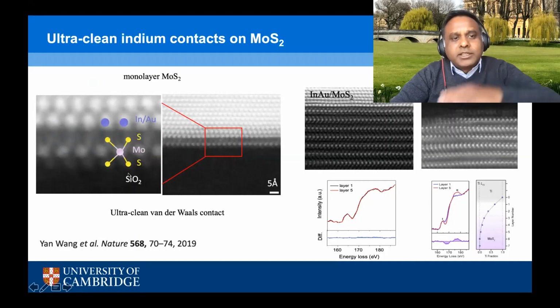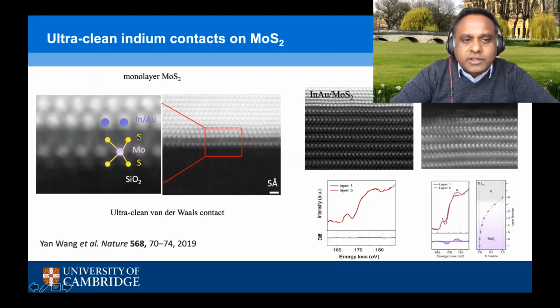And so these are cross-sectional TEM images of MoS2, right underneath the contact. This cross-sectional TEM is taken from a device that we tested, got the IV characteristics from, and then did cross-sectional TEM to look at the interface between the MoS2 and the indium electrode. What we found is that there is a clean van der Waals interface, and the reason we call it a van der Waals interface is because of the electron energy loss spectroscopy results.